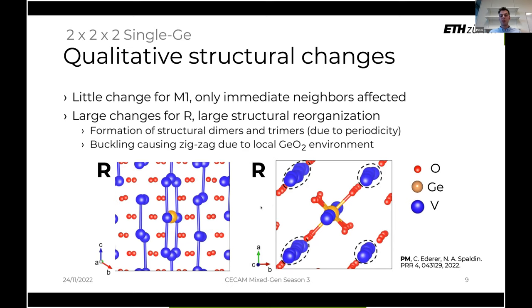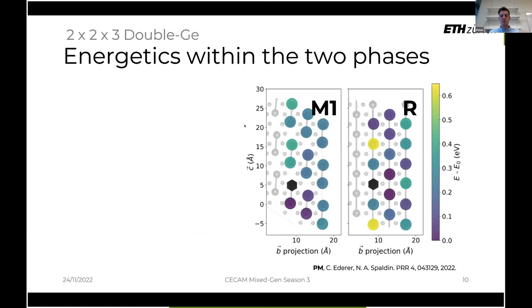So that's why we move on to our larger cell, where first I want to show you the energetics: if we put the germanium atoms in certain positions, which configurations are really the lowest energy, which are the ones that we really should be interested in. And this I tried to show with this color map here, where the monoclinic phase is on the left and the rutile phase is on the right. And with the black hexagon, I denote a germanium atom, which we retain in the same position always. And then we add the other germanium atom somewhere else in the cell, and then color the dot corresponding to the energy of that configuration.